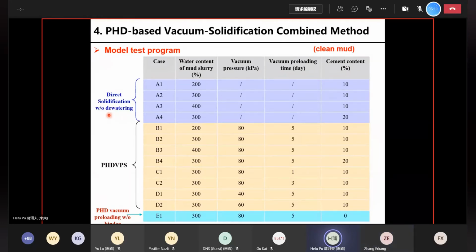In the first case, we use direct solidification. In this case, the mud slurry was solidified at a very high water content without prior dewatering. So as you can imagine, it will have very low strength after the solidification. At the bottom, we also have the PHD vacuum preloading method. In this case, it has no binder, just vacuum preloading, same as in section 2 of my presentation earlier. And in the middle, we have this PHDVPS method, which is a PHD-based vacuum solidification combined method. In this case, we combine the one on top and the one on the bottom. We test the different initial water content of the slurry, different magnitude of vacuum pressure, different vacuum preloading duration, and also different cement content. But due to time limit, I'm not going to present all of them.